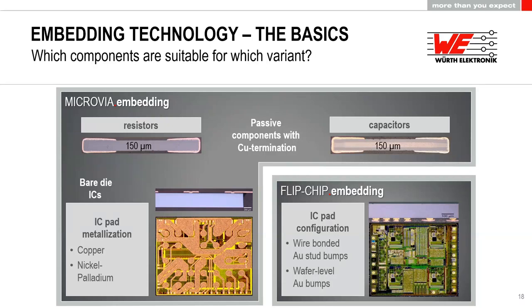From a microvia embedding point of view and from a flip chip embedding point of view, we are using either components with specific metallizations like copper or nickel palladium for the active components, or with copper terminations from a passive point of view. There are several vendors out there who offer resistors and capacitors with these copper terminations. And as I already said, if you have a bare die which previously was meant for wire bonding, for example, there might be subcontractors out there who can do, like you see here in this microscope picture, a so-called RDL, a redistribution layer with copper, so that you have a copper surface with big enough pads which can be contacted by microvias.